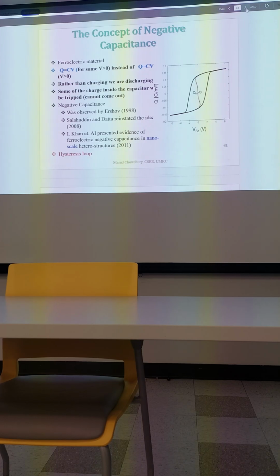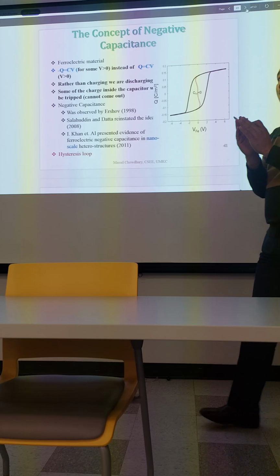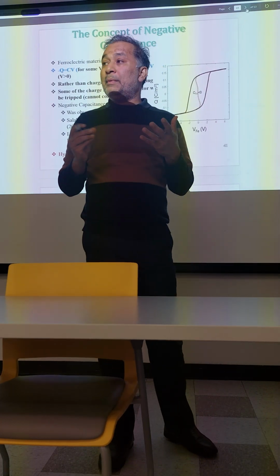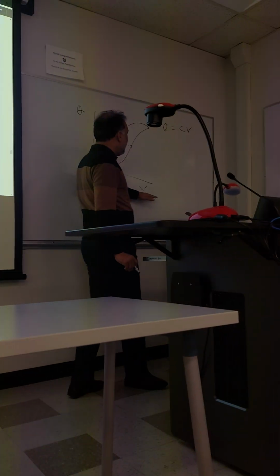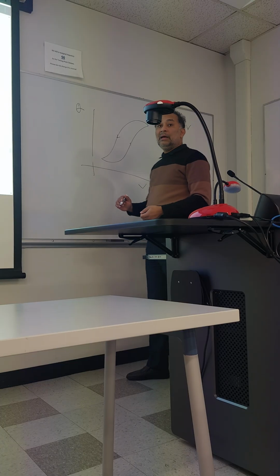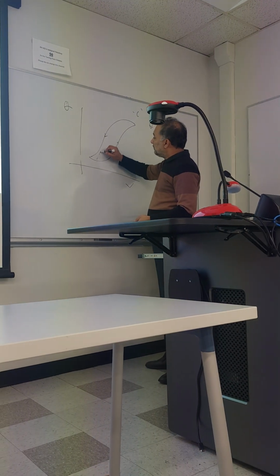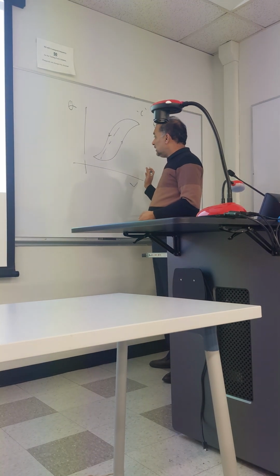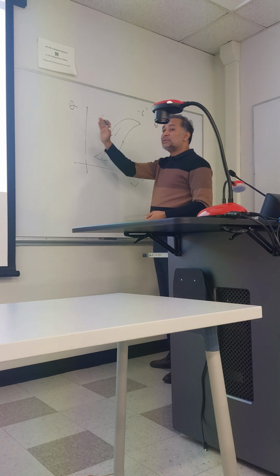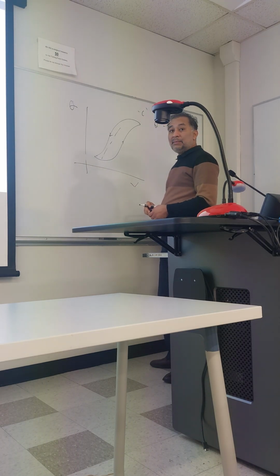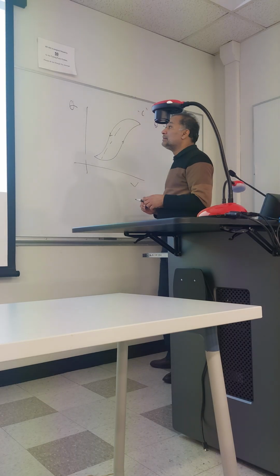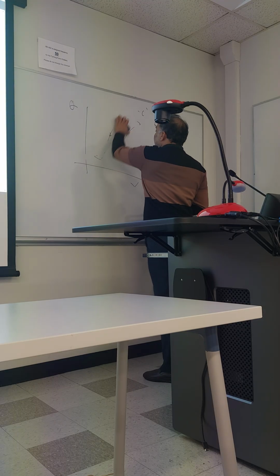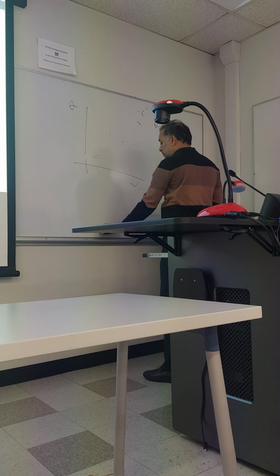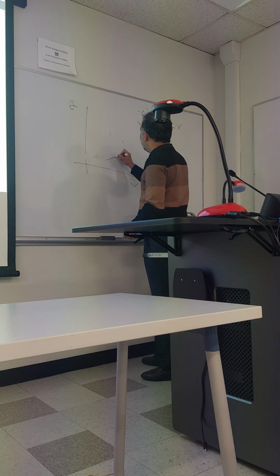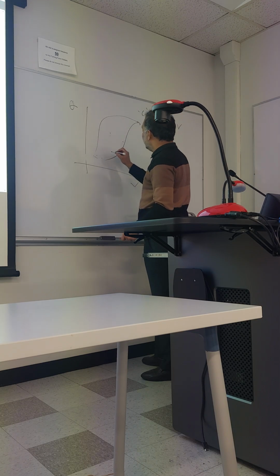For ferroelectric material, it will show a hysteresis behavior. Hysteresis means a loop appearing in the CV characteristics or IV characteristics. It will follow one path as you increase the voltage, and a different path as you decrease it, but every time the slope will be like this. That means higher voltage means higher charge accumulation, lower voltage means lower charge accumulation. But in some cases, it is observed that some ferroelectric material will have a hysteresis loop in such a way that at some point the trend will be like this.